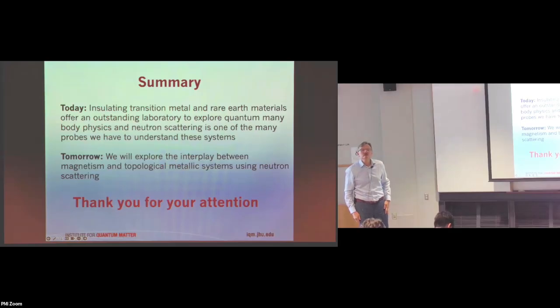Is it easy to work with erbium oxide? I don't know. I was told by experimentalists that it's not easy to work with erbium oxide crystals. I mean, from a neutron perspective, it's fine. There's no problem. Absorption can be a problem because some elements absorb neutrons, but I don't think erbium has much of an absorption. And even if it does, we just go to another isotope if we can afford it, and then we can keep going. So I think erbium oxide should be fine, and one just needs about 1 gram of powder. Thank you so much.